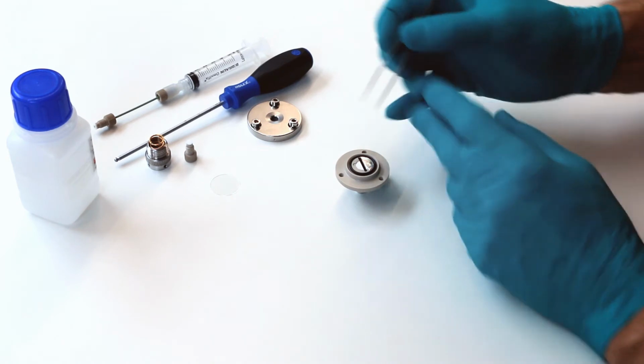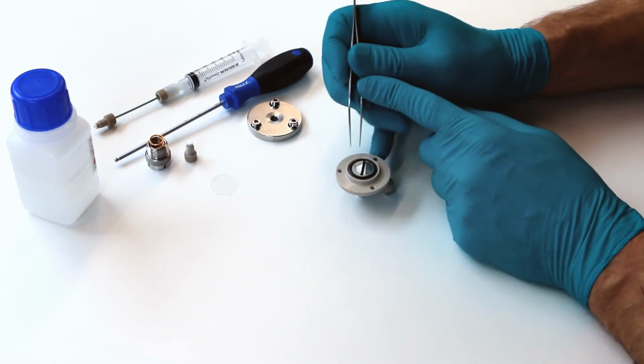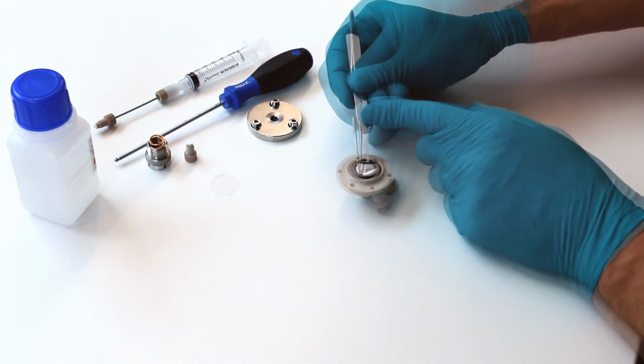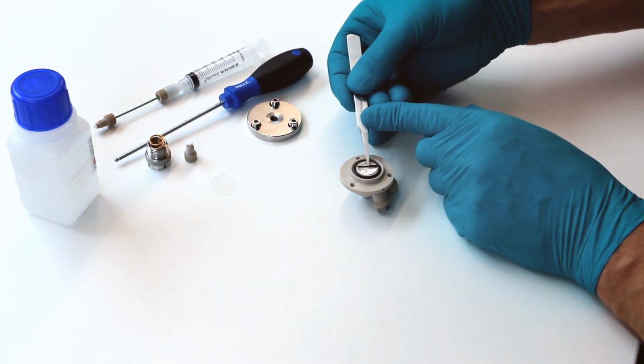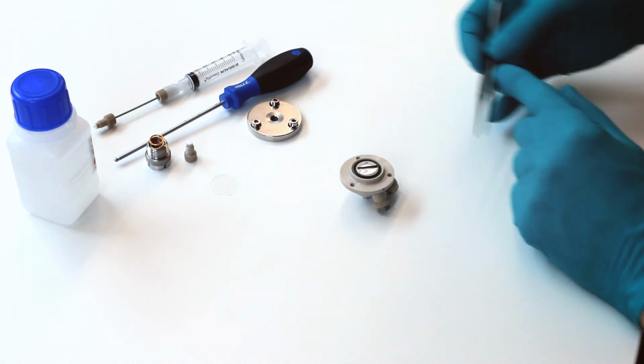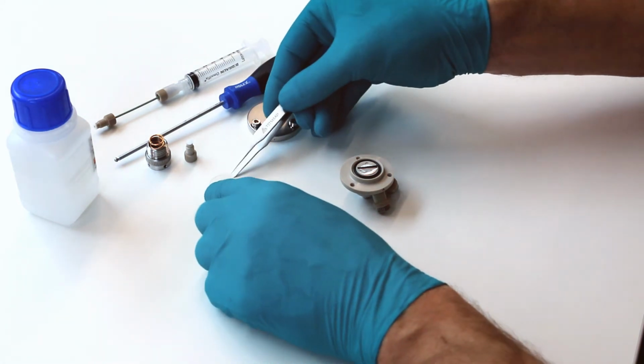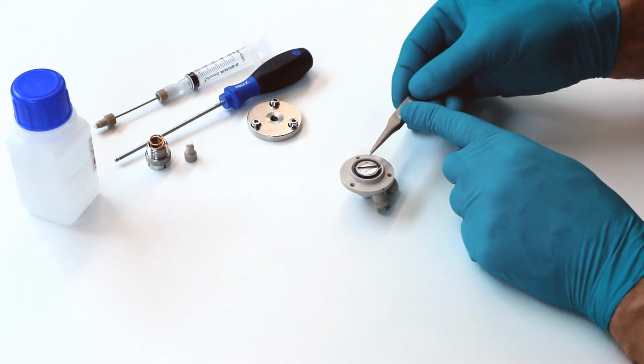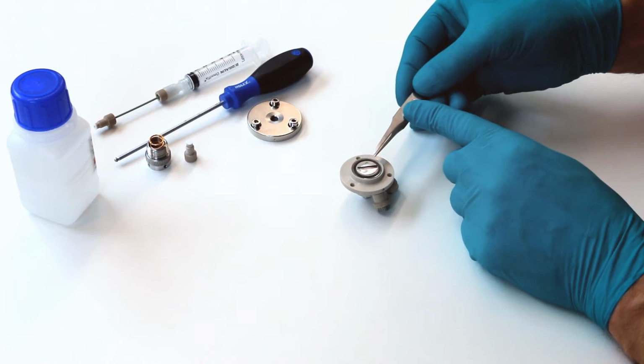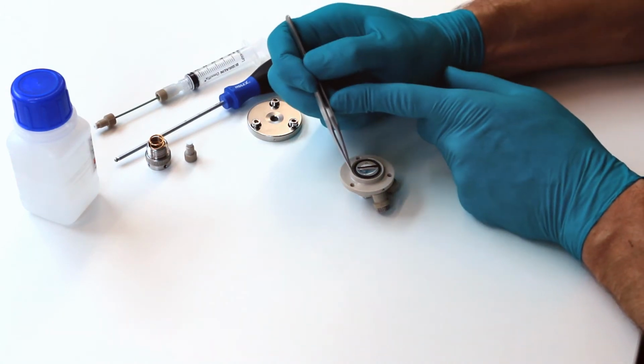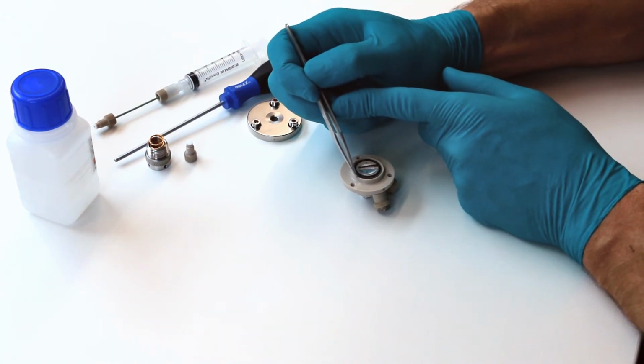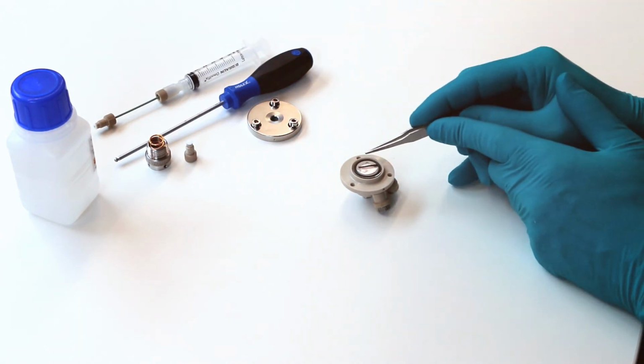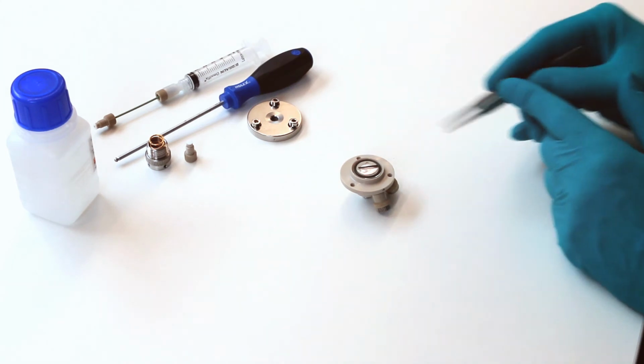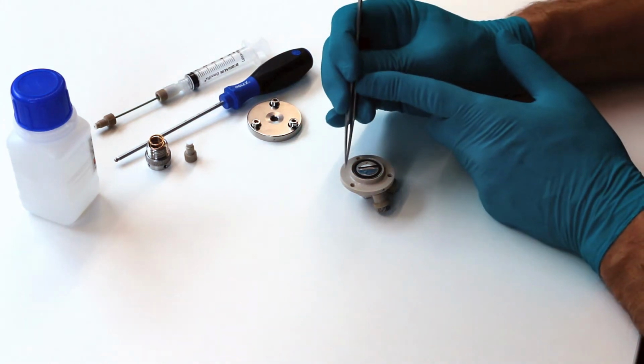Besides the lithium metal foil, place the graphite electrode with an active layer pointing upwards towards the window, which is finally put in place. Make sure the window is in the center position, as you may otherwise break the window when attaching the cell lid.